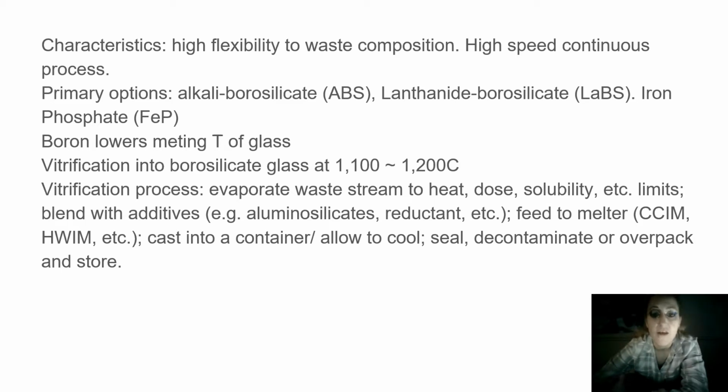Vitrification process: evaporate waste stream to heat, dose, solubility, etc. Limits: blend with additives, for example aluminosilicates, reductant, etc. Feed to melter, CCIM, HWIM, etc. Cast into container / allow to cool. Seal, decontaminate, or overpack and store.